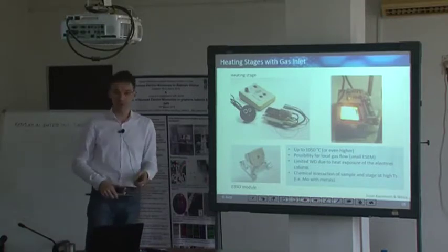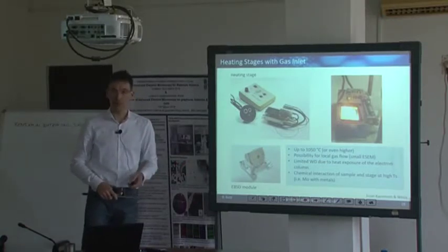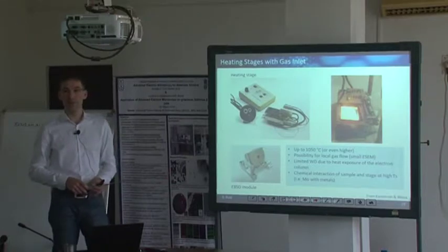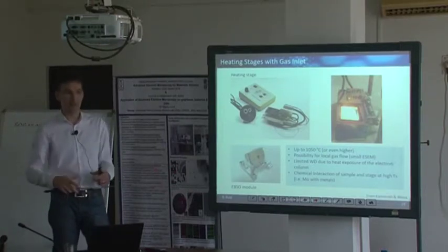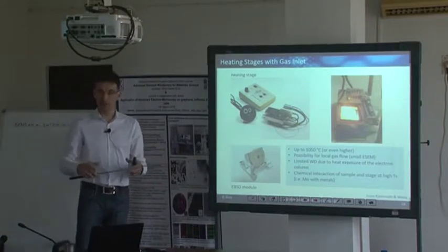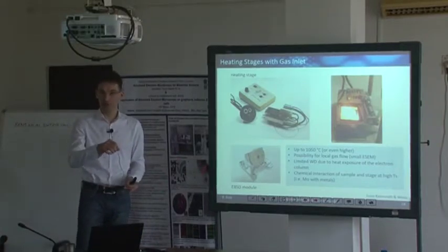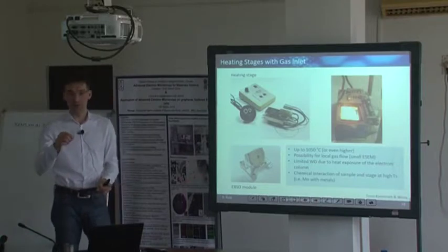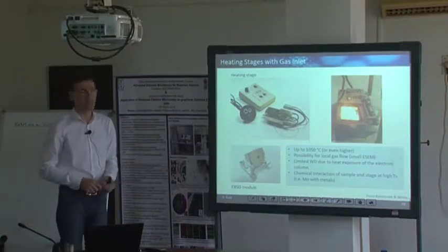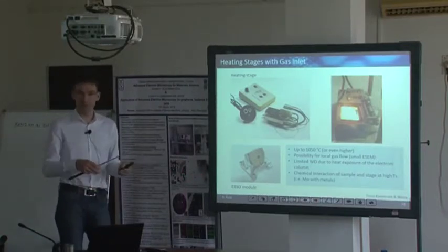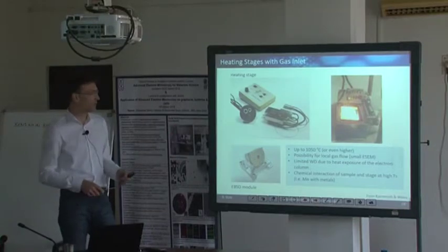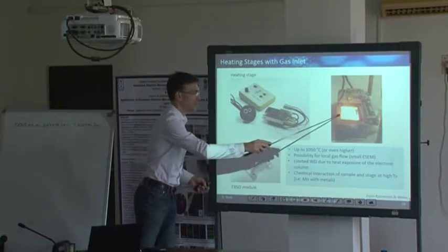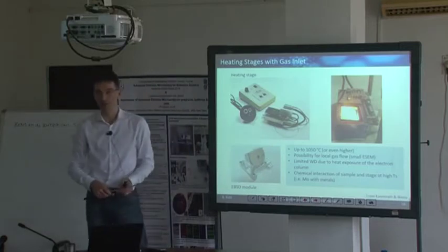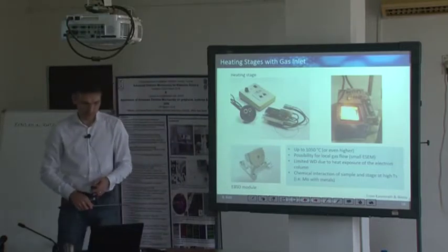So one of our students spent a lot of effort to achieve that accuracy in Debye diffraction. Just by this ring pattern acquisition of nanoparticulate materials, we were able to measure the temperature with an accuracy of 3 to 4 Kelvin. You need ways to measure the temperature on a local scale. You should never rely just on this preset value or on the measurement of your heating device.